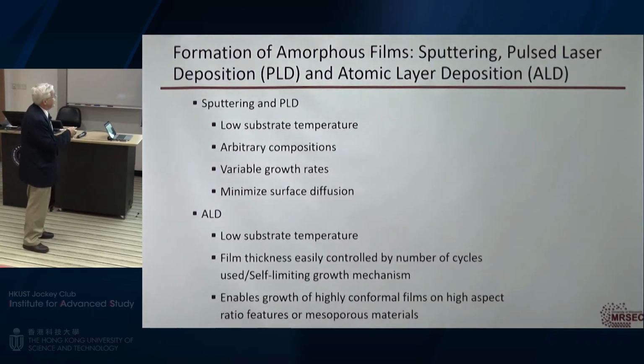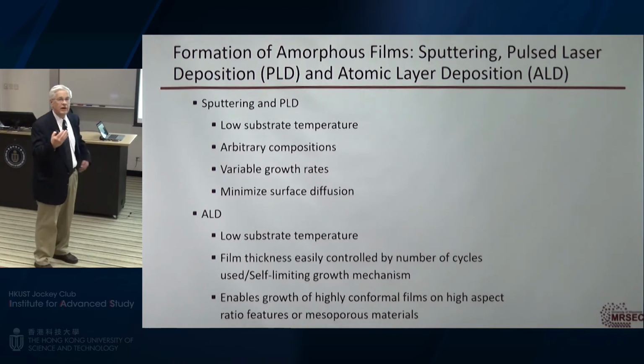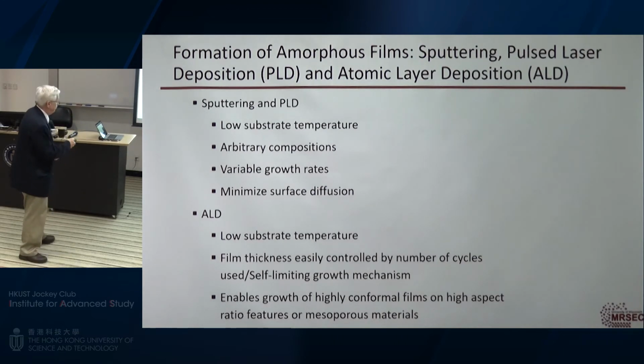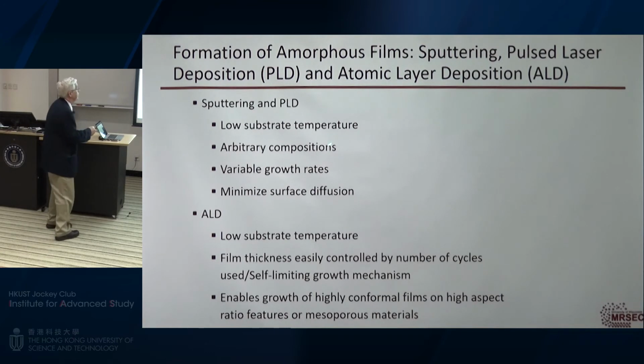So the way we make amorphous films is we sputter them or use PLD. You can put down arbitrary compositions. It depends on the target. And you can do that because the atoms come down and it's very, very cold, and they basically just stick. So it's like spray painting. And so I can make arbitrary compositions that, if it was crystalline, would have an interesting property.